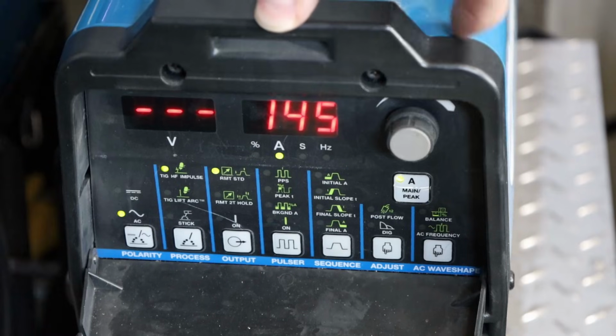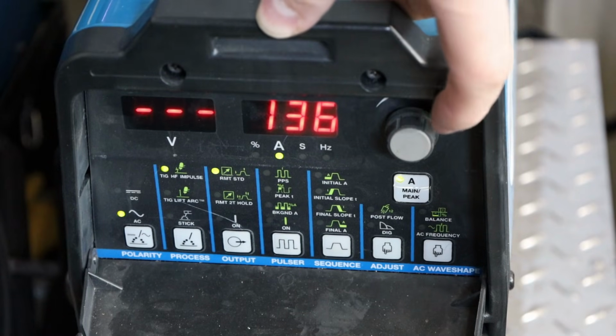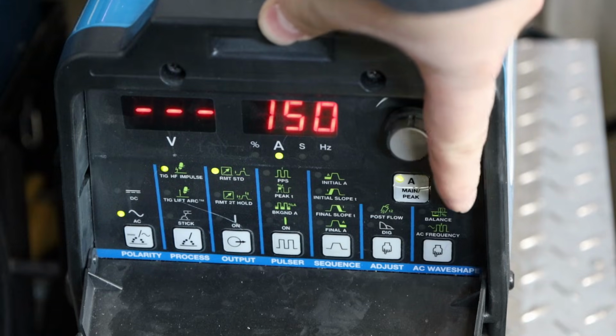So we're going to be doing our work on 1/8 of an inch material, and we're going to set the machine here right to 150 amps. Now, this is a good setting for me because I have a foot pedal that'll let me back off and vary the amperage a little bit, but I'll be using most of that 150 amps at different points during our welding today. So that's one of the easier settings to get a feel for whether you're running too high or too low.